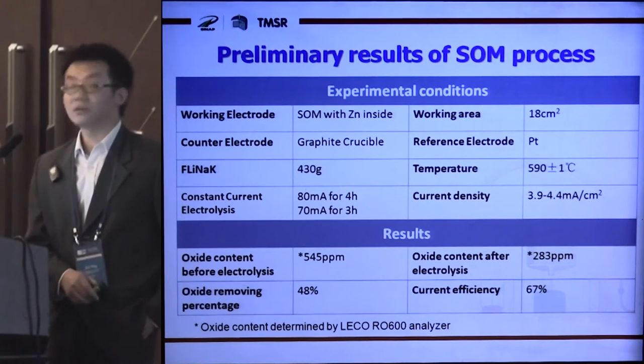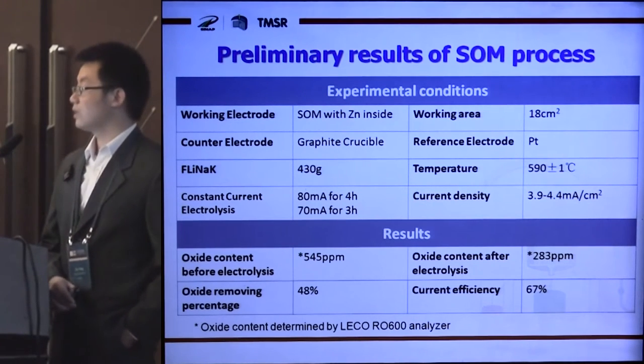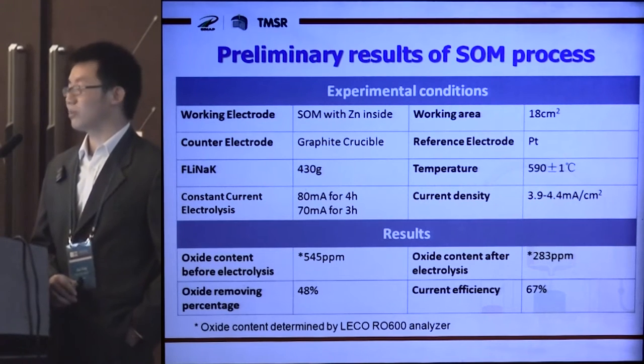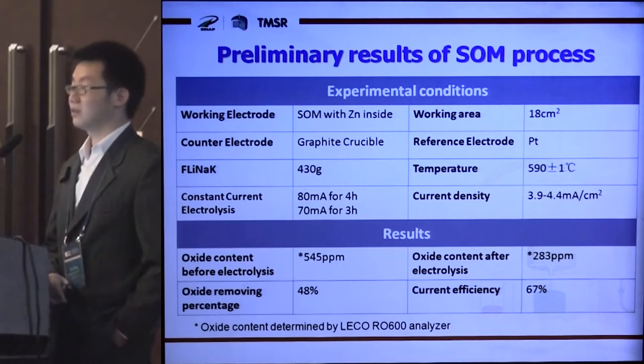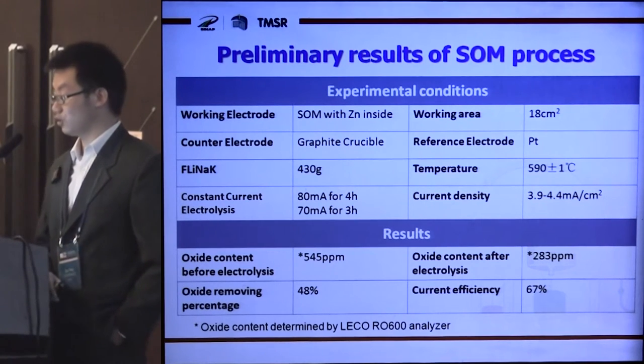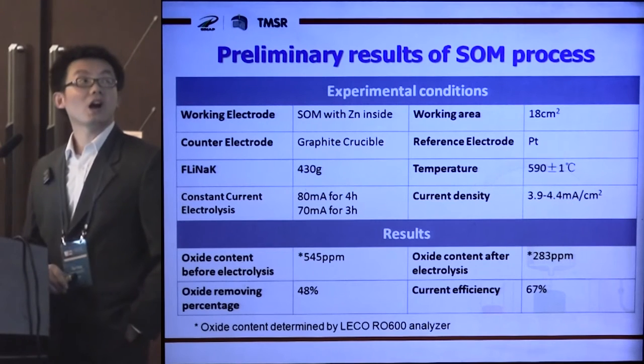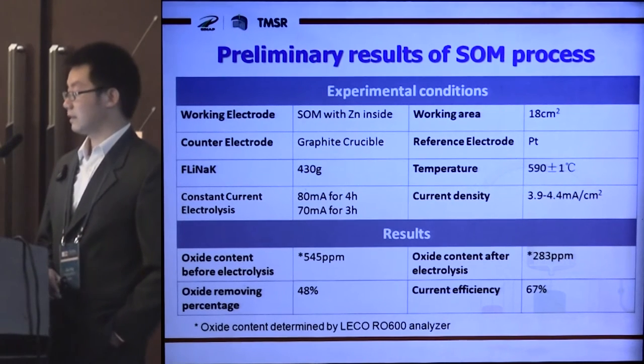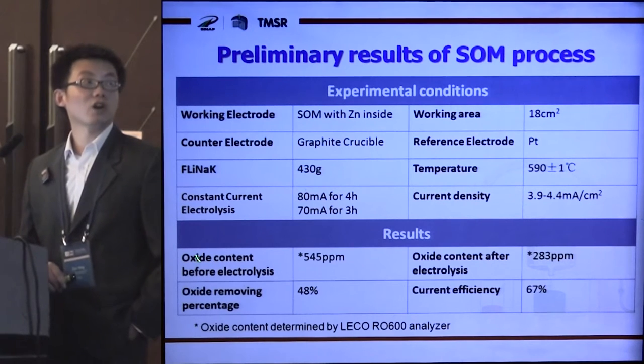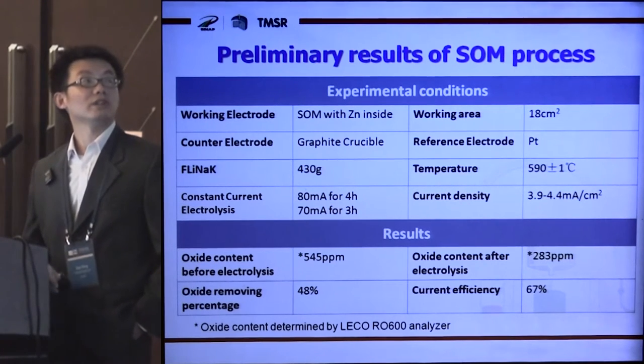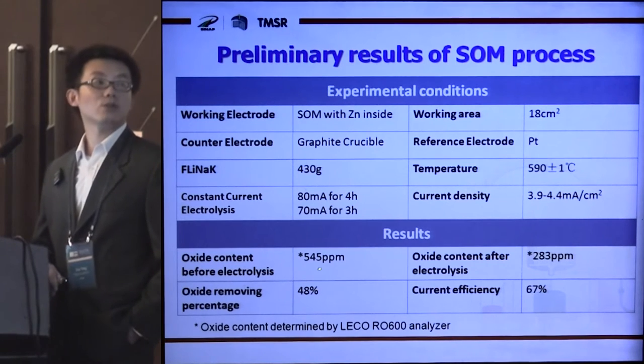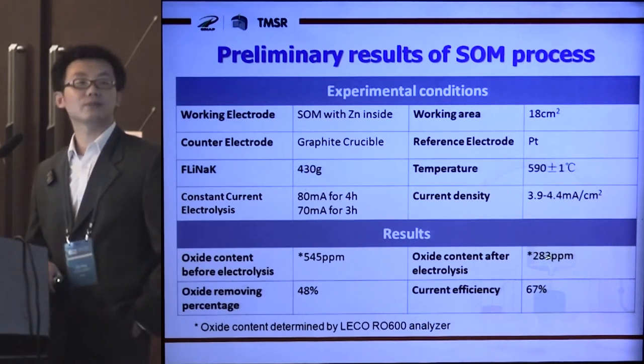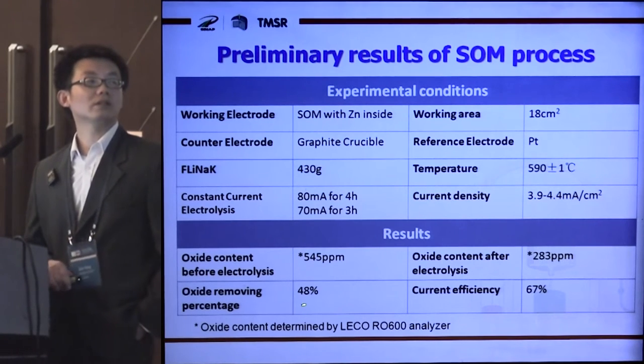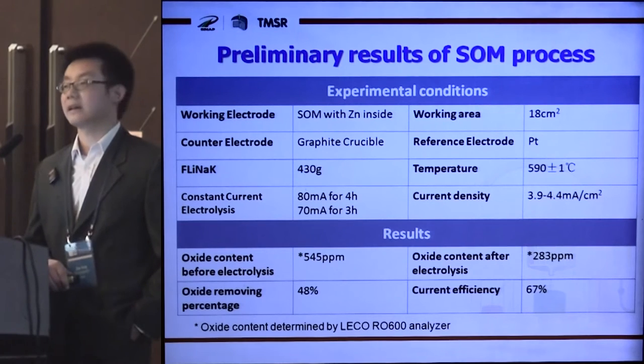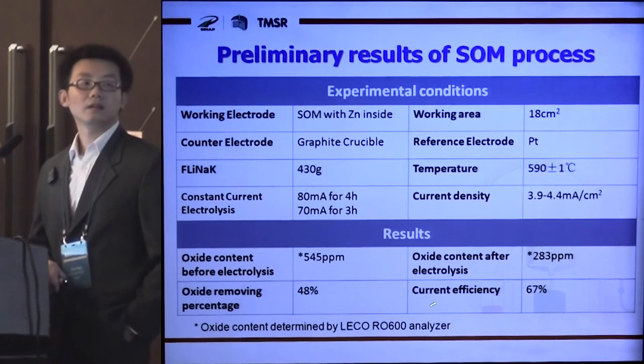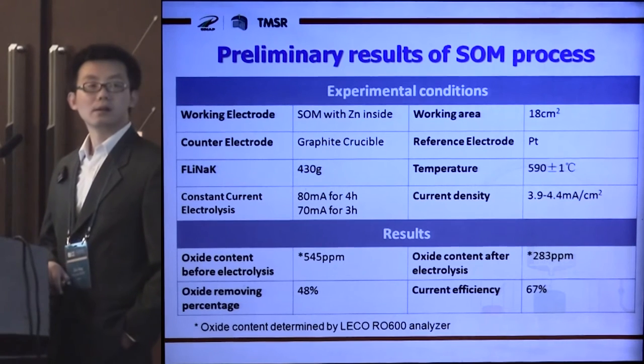The research work about the SOM process is ongoing in our laboratory, and now I can only provide preliminary results. The above is the experimental conditions. After 7 hours of constant current electrolysis, the oxide content in the FLiNaK molten salt decreased from 545 to 283 ppm. About 48% of the oxide was removed, and the current efficiency was 67%.